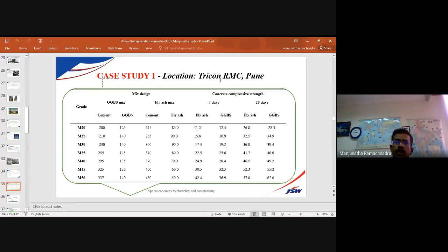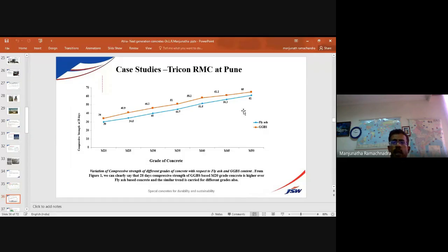So one of the examples, a case study we have done with fly ash and GGBS mixes. You can look at the strength, 7 days, 28 days compressive strength of M20 to M50 grade concrete. We have studied that GGBS, having more cementitious content, calcium oxide 40%, gives a little bit more superior compressive strength compared to your fly ash mixes. This is the graph, fly ash graph and GGBS graph. You can see the GGBS product giving better strength compared to fly ash concrete.